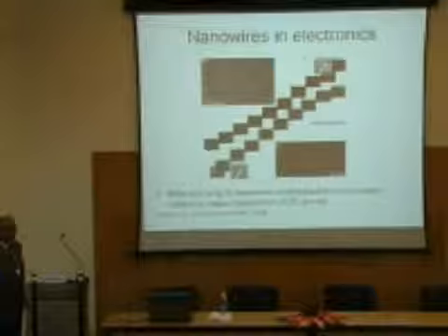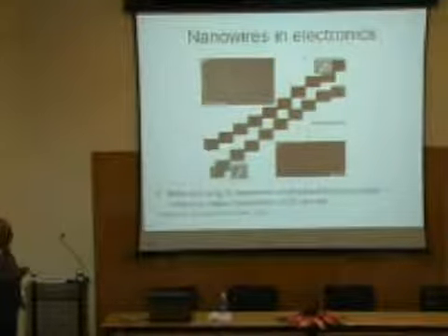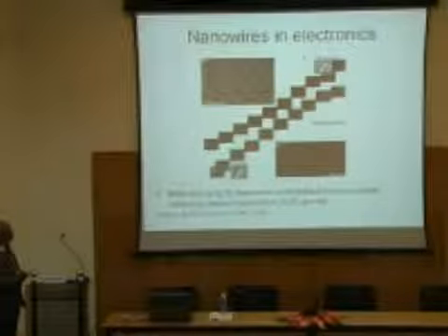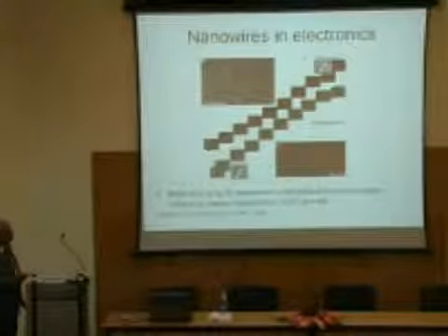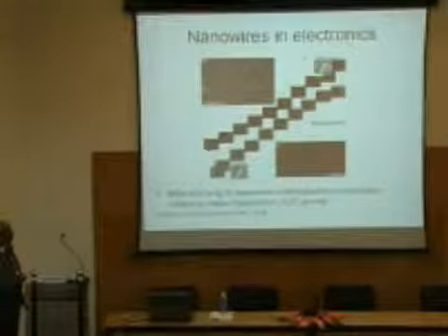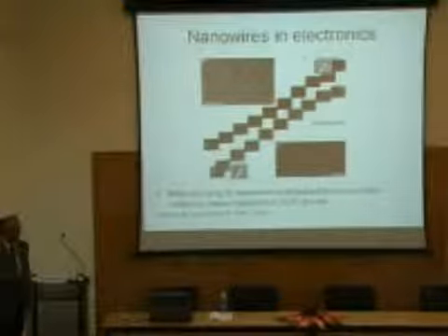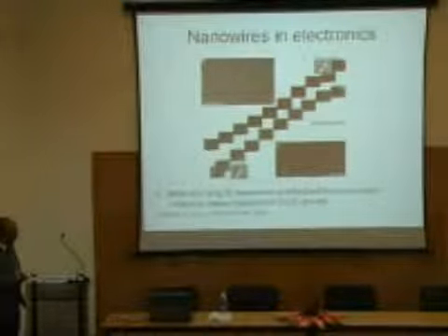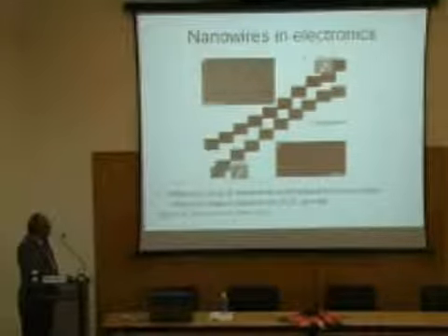Instead of making large crystals, you have a very small diameter but very long wires. And these are TEM pictures to show that the wire is very uniform by this method. You can see at one end it is 33 nanometer, and I think on the other end it is 32 nanometer. So you can precisely control the diameter of the nanowire by this standard vapor liquid solid method.